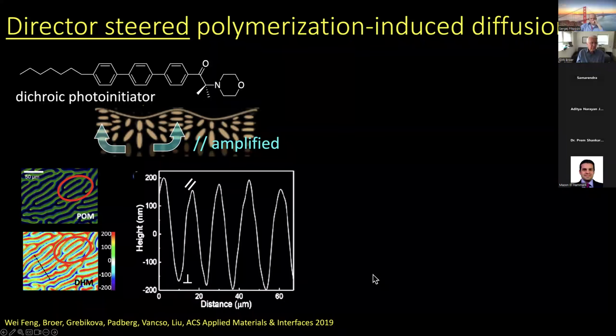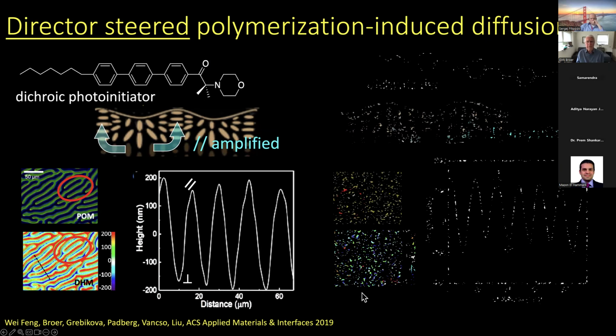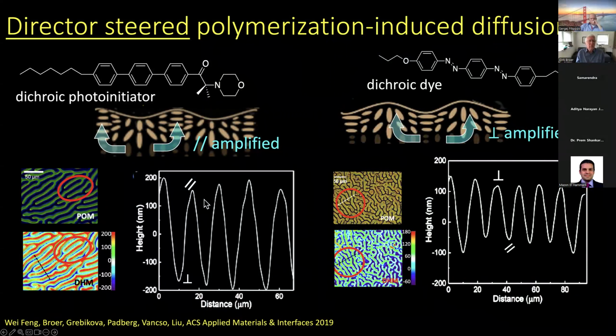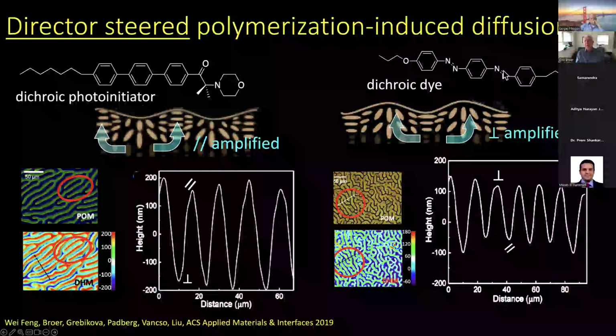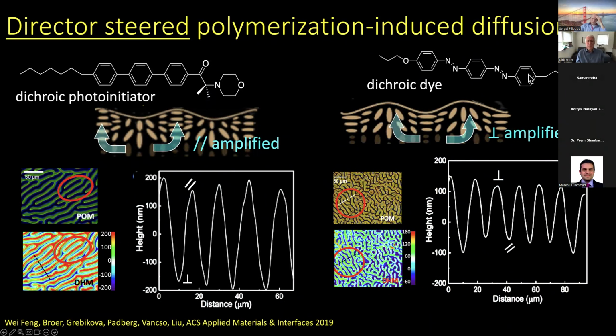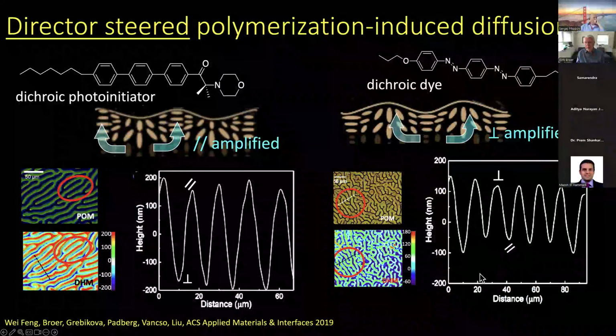This is one way of doing it. This is work by Feng in our group. Another way is not using this dichroic photoinitiator, but now just going to a system where you have added some dichroic dye. In that case, you create just the opposite. The absorption of the light is then higher in the planar area, and the light intensity is lower in the perpendicular area, where the dye does not absorb the light so much. Then the opposite happens to what is happening here. So during the polymerization, the molecules tend to diffuse to the homeotropic area, and now you have a system where you have hills where the molecules are perpendicular, and you have valleys where they are oriented planar.